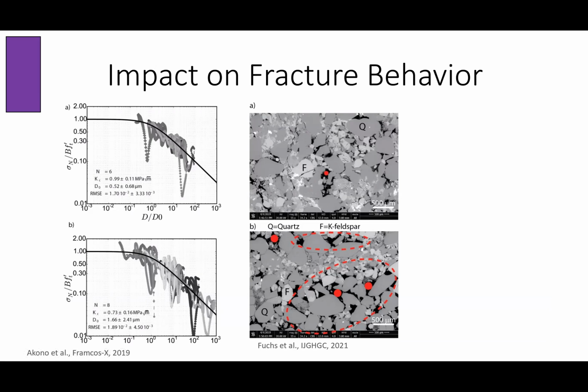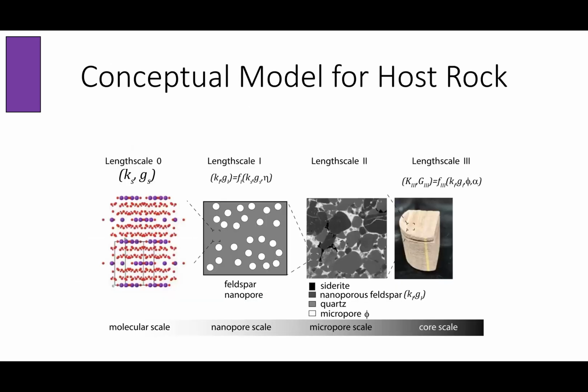Now we are able to link it to microstructural changes. So this is a SEM picture of the intact rock and SEM images of the rock after alteration. After alteration, we see an increase in porosity and we have the formation of channels. And this is actually linked to mineral dissolution reactions that are occurring. So then we wanted to look at what is happening, what type of mineral dissolution is actually occurring in this case.